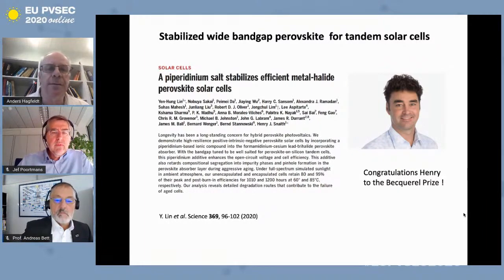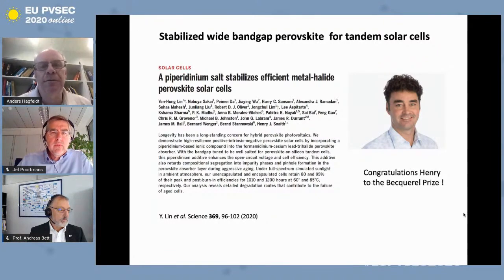And here they look into stabilization for tandem devices. That means that we need to go to higher band gap energies, and then you mix in bromide, and then you have an iodide bromide mixture, and they have a photo effect that they segregate, and you have stability issues for segregation due to light. And here they have managed by an ionic salt, piperidinium salt, to stabilize that phase segregation and reach thousands of hours at ambient temperature of stability, which is very promising, and then as a top layer on a tandem cell.